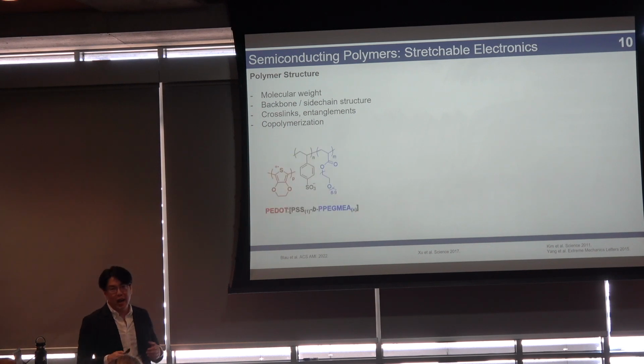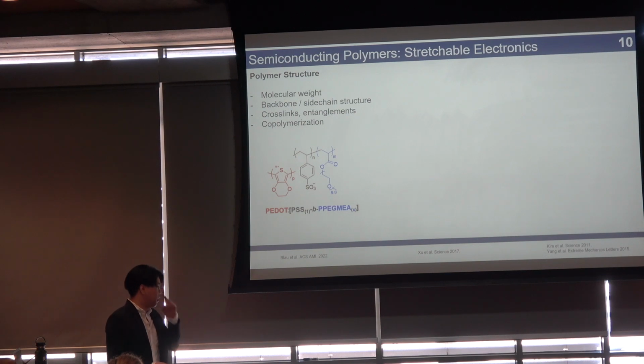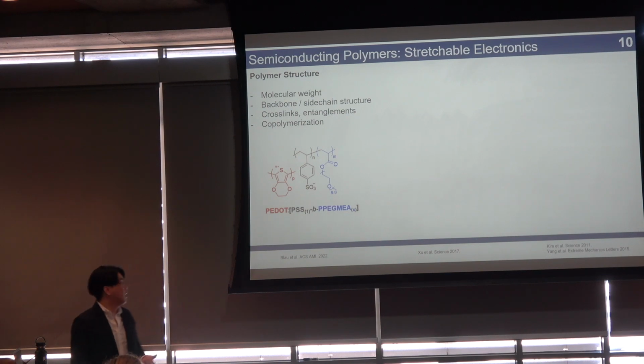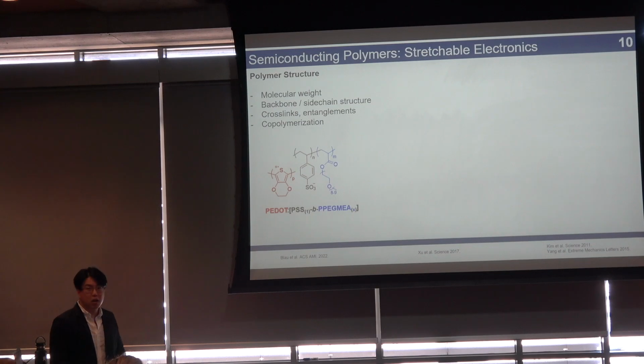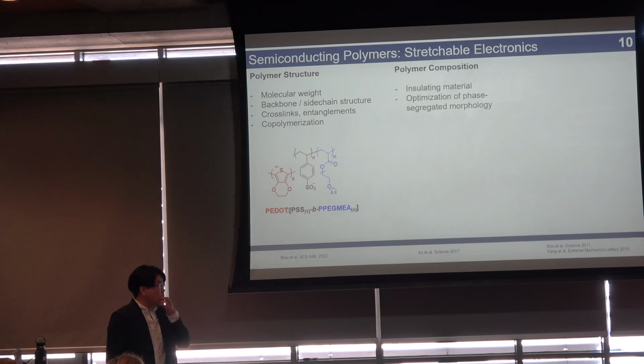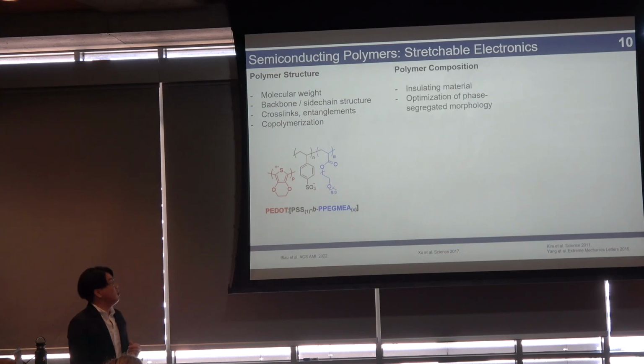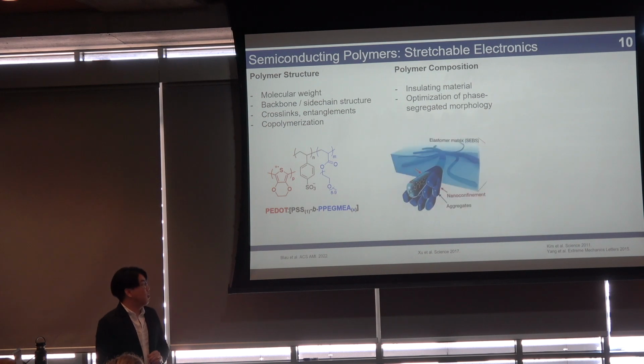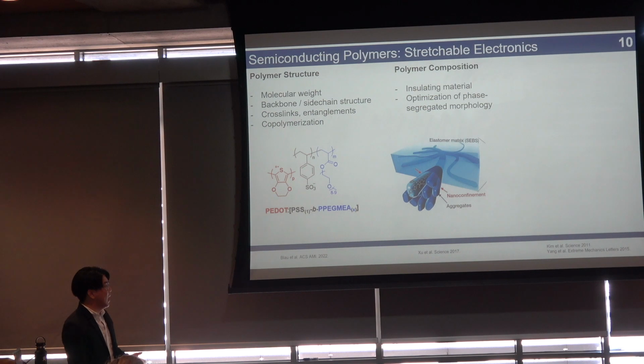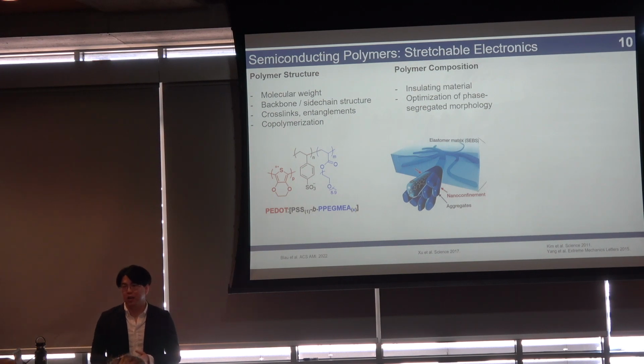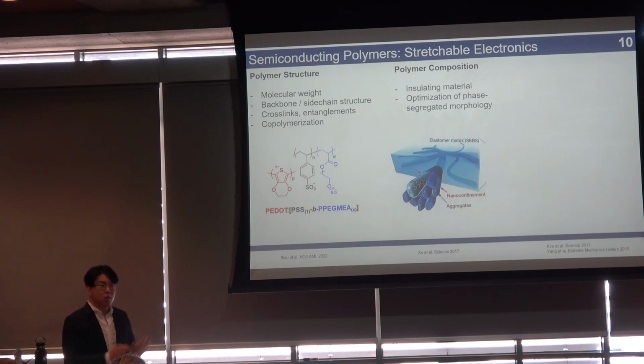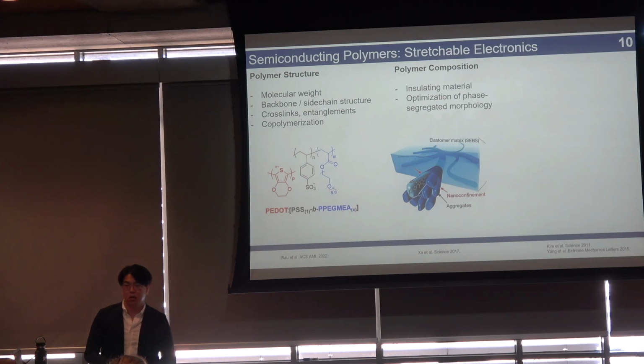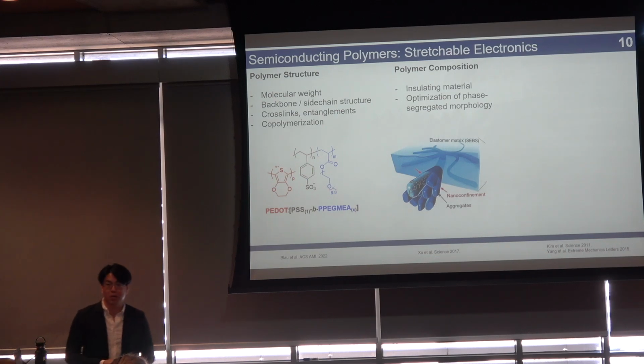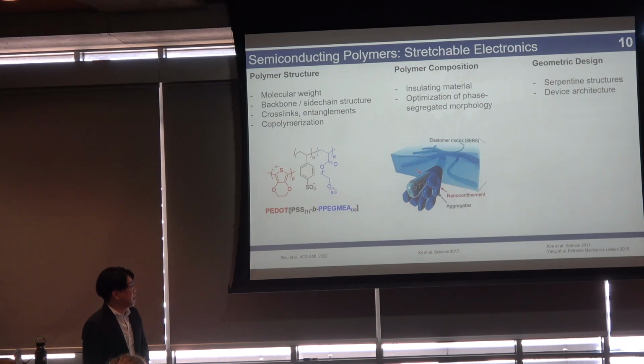For example, you could attach a very stretchable insulating block onto your semiconducting polymer. You can also mix things together. You can blend your polymer. And for example, if you blend a semiconducting polymer with an insulating polymer, SEBS, you can create these nano-confined domains that still transport charge while still retaining the mechanical properties of your polymer matrix.